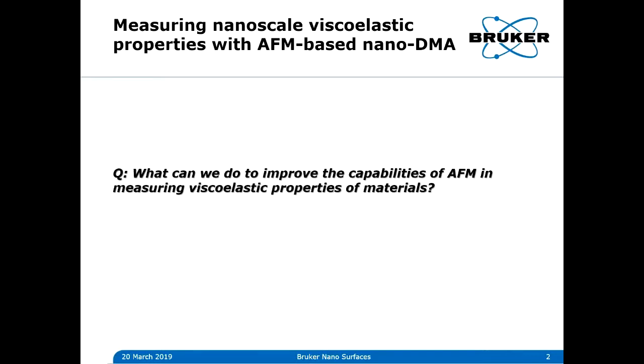As Dalia mentioned, we at Bruker have been working for a while to improve the nanomechanical measurements with AFM. In the last couple of years, we've made significant progress in improving the system calibration through these probes. And we've also added contact resonance to allow measurement of storage and loss modulus at high frequencies. However, as Dalia pointed out, until recently, there are some important gaps between the needs of polymer rheologists and the capabilities of atomic force microscopy.